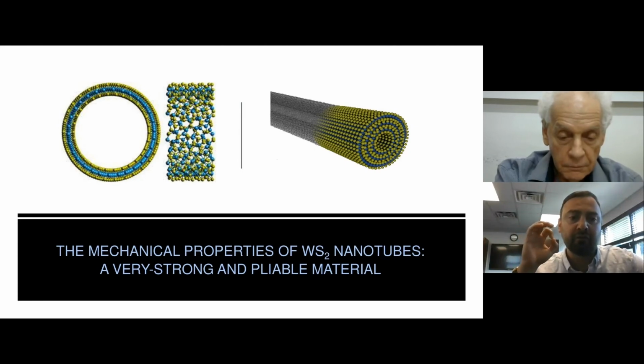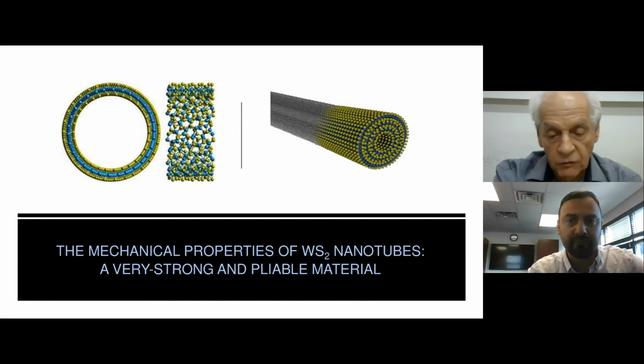...make sulfur get released? Yes, the trouble is not so much the temperature as the ambient condition, the air, because you have air around you. So if you work with a lathe that operates in an inert atmosphere, you can go to much higher temperatures compared to an air atmosphere.